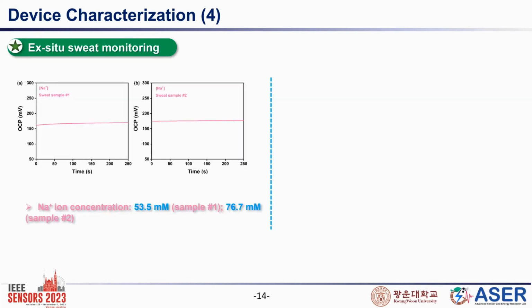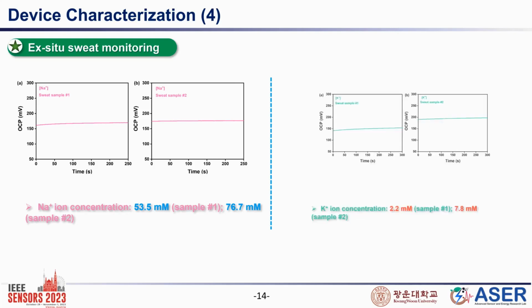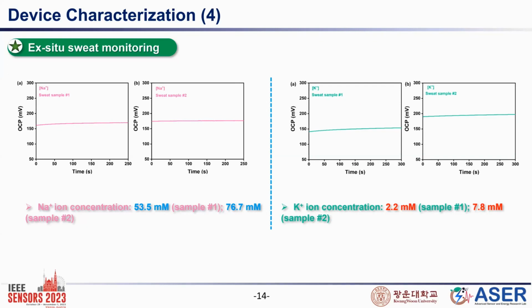And last of all, we have measured the sweat electrolytes using our sensor. To do this, we collected some sweat from 2 volunteers who went through hard exercise, and we collected some sweat, and used the bench-level test to see the quantification of the electrolytes. So these are the OCP responses we have taken from the electrochemical workstation, and using our fitting equations, we have calculated the concentrations of sodium ion. From the 2 volunteers, volunteer 1 has 53.5 millimolar, and the other has 76.7 millimolar sodium concentration. And in parallel, we have done the potassium ISE that gives us 2.2 millimolar and 7.8 millimolar concentration.